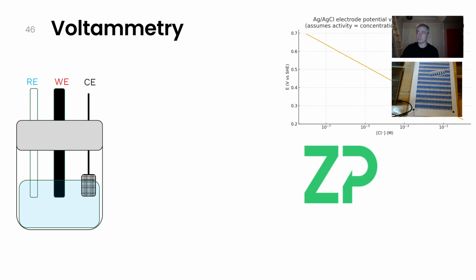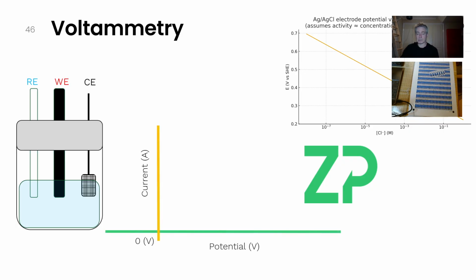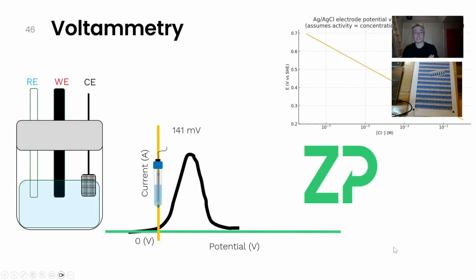What that would mean is that you would maybe do the voltammetry on a particular molecule. You would have a true reference electrode in there, and you would say, well, the peak potential in this case is 200 millivolts versus the silver chloride reference electrode with a 1 molar chloride concentration. If, for some bizarre reason, you decided to dilute the chloride concentration in that reference electrode by 10x, then the potential would shift by about 59 millivolts, and you would then report that my peak potential is 141 millivolts versus silver chloride in a 0.1 molar chloride concentration.